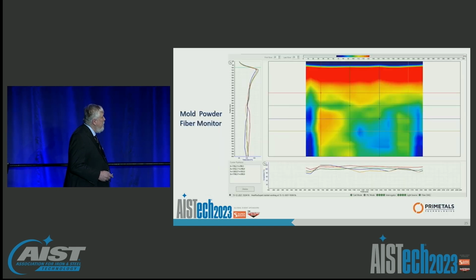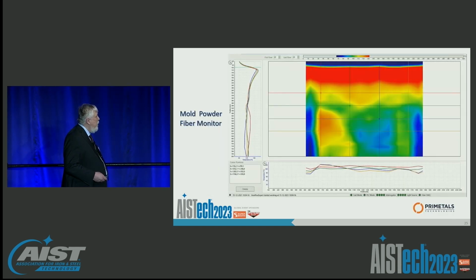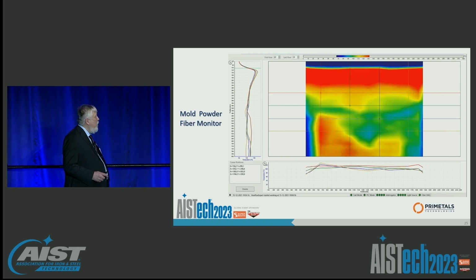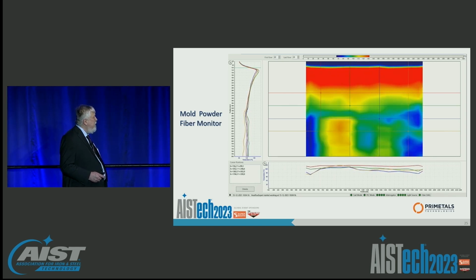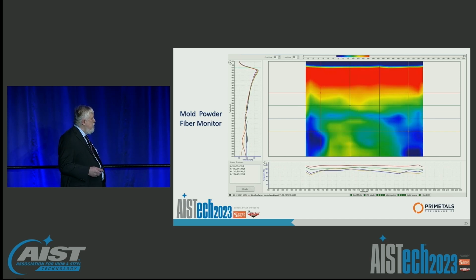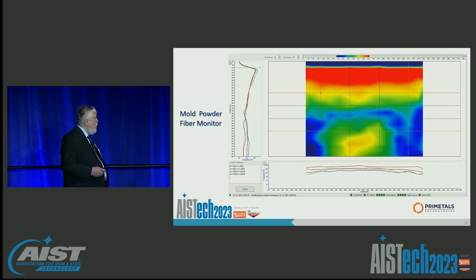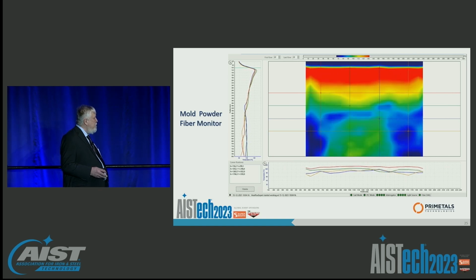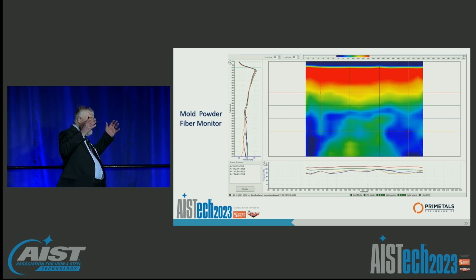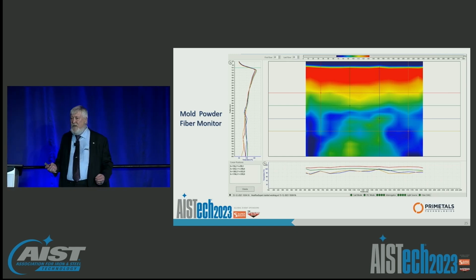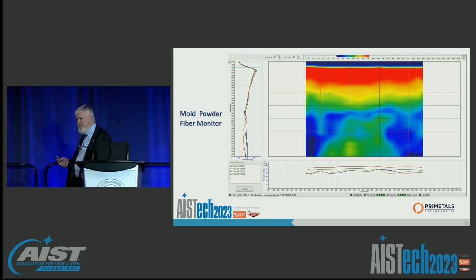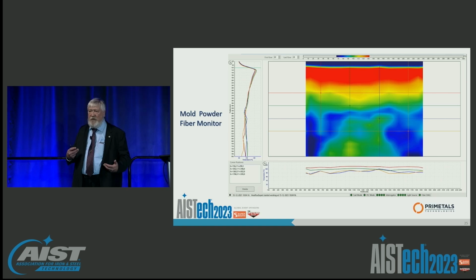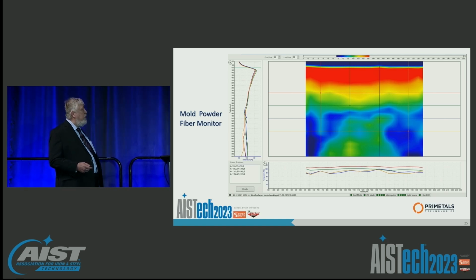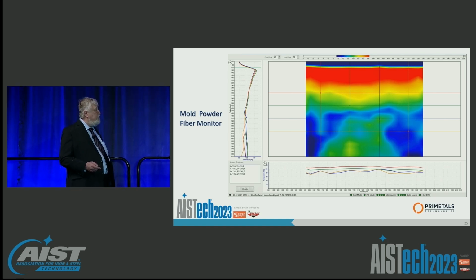And I think I've also, this is actually a video just showing the dynamics of a lower part of a mold that exhibits this periodic sheeting behavior. You can see it's not always uniform. This happens to be sheeting in the lower part of the mold, but we can actually watch that instability. And a lot of this has to do with how the flux is designed, how thick and rigid the flux film is, and its ability to resist shear, essentially the stresses associated with the casting process.